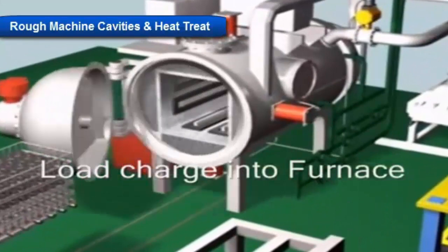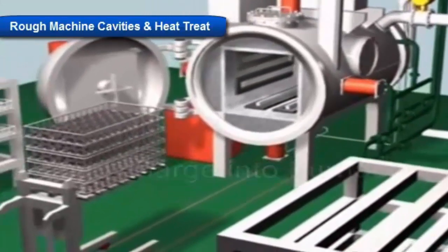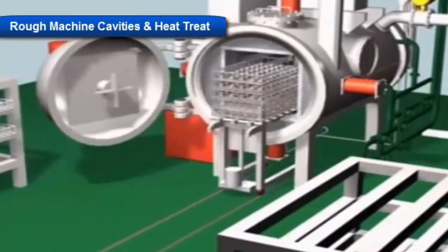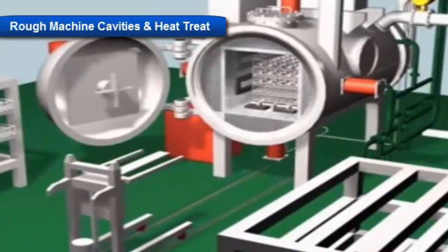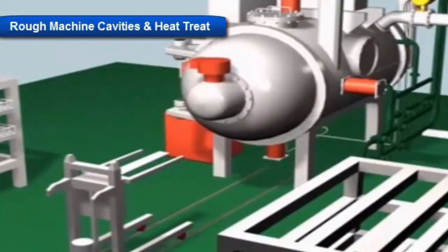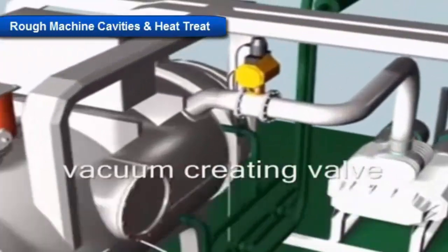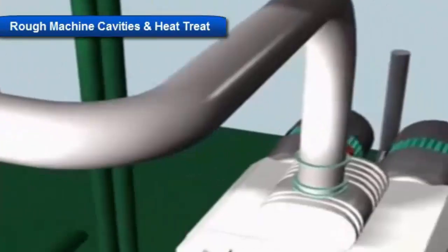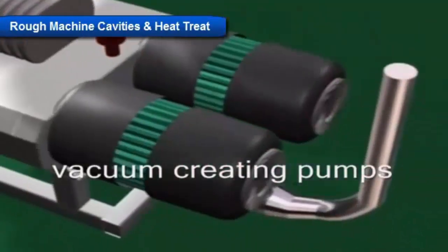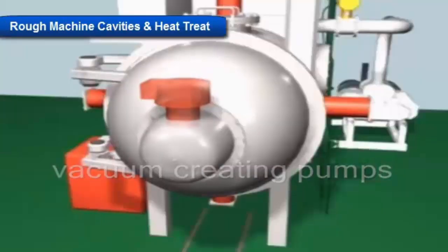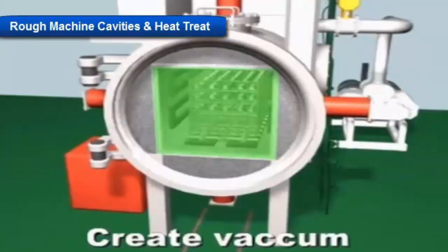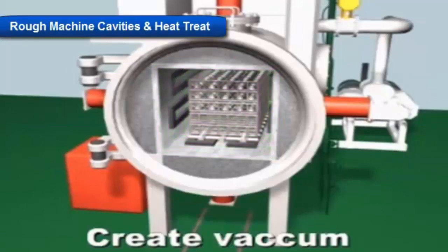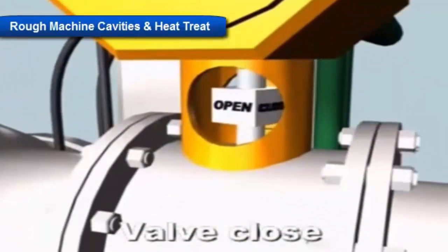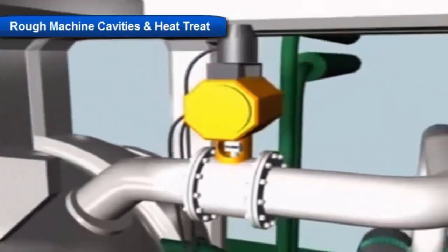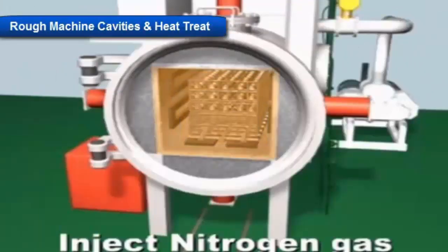So typically, for the premium H13 that we use, we use a vacuum heat treat process. They'll drop the pressure in the system to pretty near vacuum, and then they'll inject it with usually nitrogen or something like that, something that's going to be non-reactive with the steel. And then go through the heat treat process.